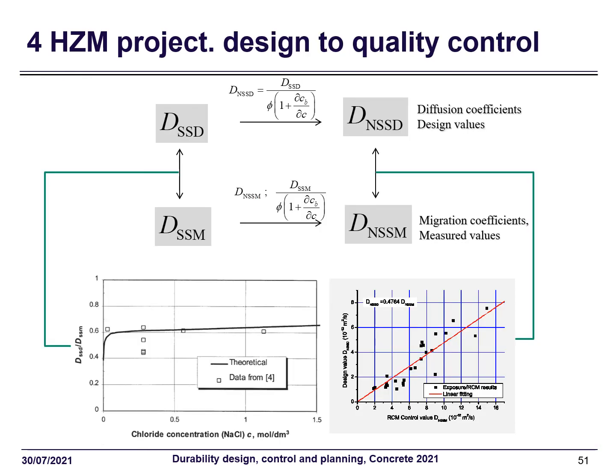And when we go to the construction phase, the problem is our value from the model is the diffusion coefficient. But in the laboratory, at the quality control level, we have the migration values. These two values are not equal to one another. So we have to make the conversion. That means we reconstitute the long-term exposure specimens in the laboratory, and we redo the migration test on these specimens, and we regress the correlation between the two. In this way, we can convert the design value to the quality control value.